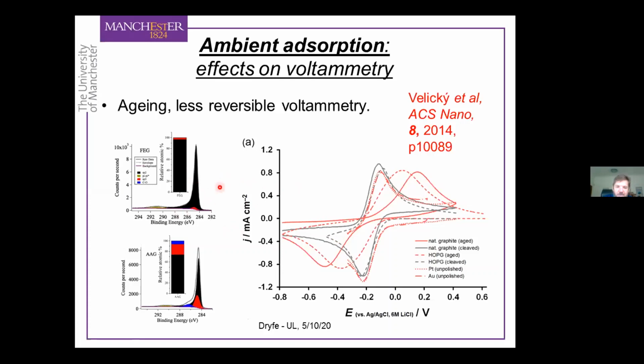And you can also see this in the XPS response. This is the XPS signal, the carbon 1s signal, of freshly exfoliated graphite. You see it's dominated by the sp2 carbon. There's only a trace of sp3 carbon, and there's essentially no oxygenated carbon in the XPS signal. Whereas if you leave that material for just a few minutes in a typical laboratory environment, you see a bit larger sp3 signal, and also the appearance of a signal due to oxygenated carbons. So these things are all saying the same thing, the XPS and the voltammetry: it's that basal plane graphite gets rapidly contaminated under ambient conditions.